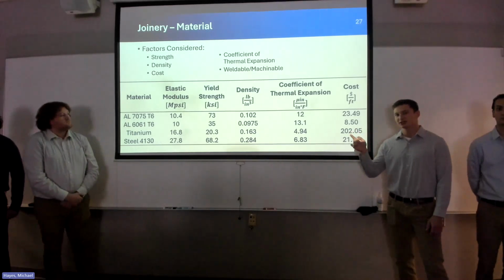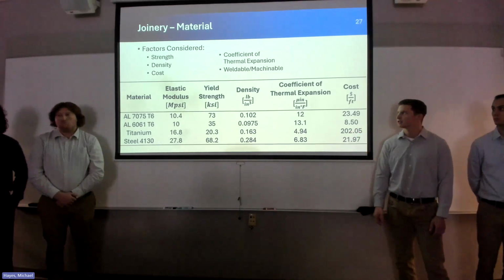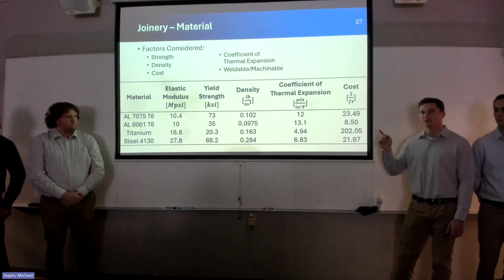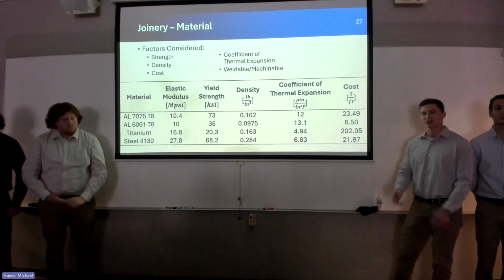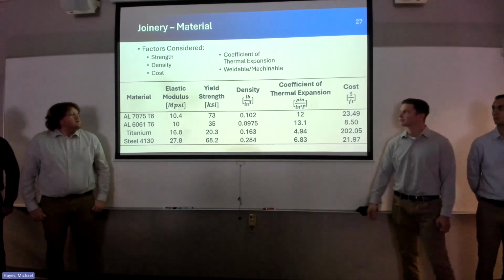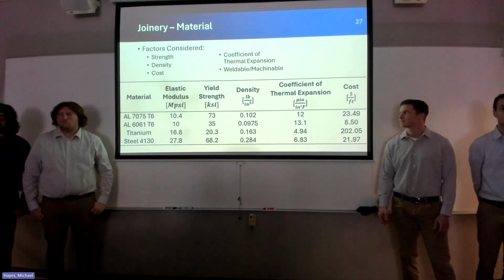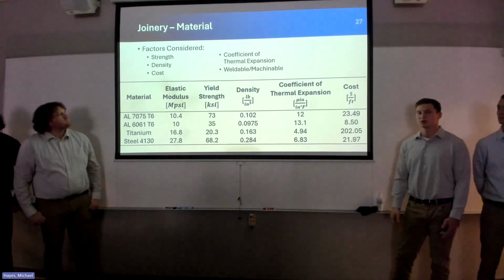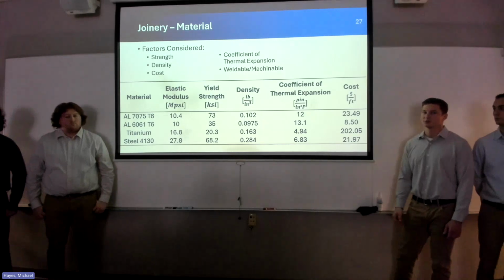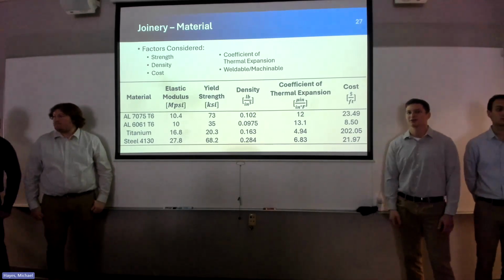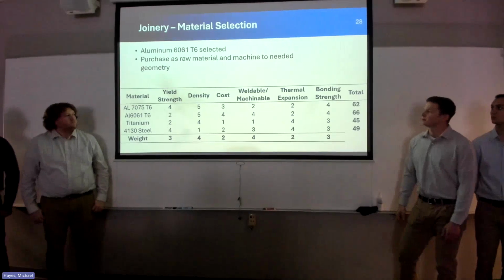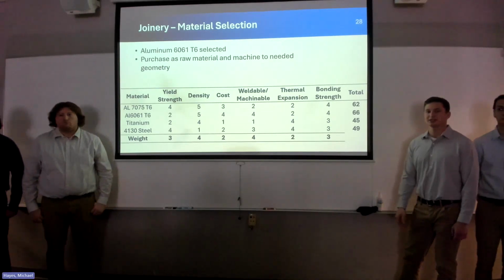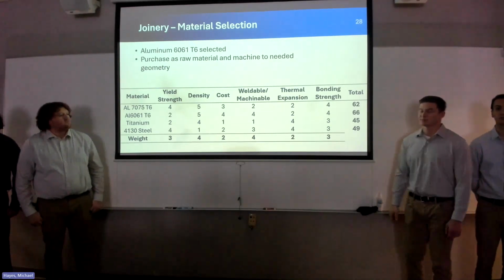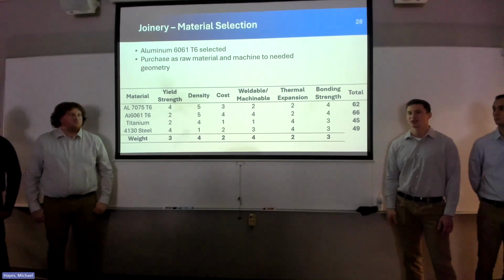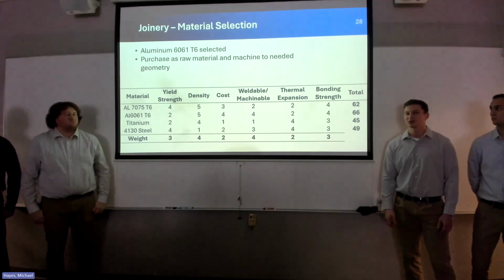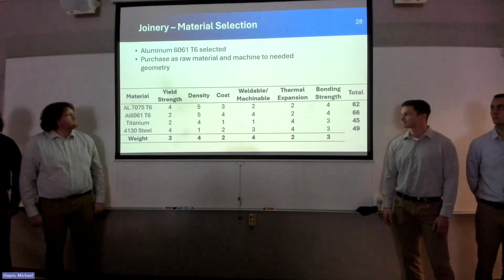Obviously, we wanted to consider the strength, density, and cost as these are main considerations. And again, that coefficient of thermal expansion, we want to make sure that it doesn't expand too much in comparison to the composite, just to make sure there are no residual stresses. Lastly, we want to make sure that it's actually weldable and machinable, as some of these geometries will be pretty complex. We don't want any work hardening limiting us in those factors. With our decision matrix, we ended up picking a 6061 T6 aluminum. This is purchased as a raw material, which we can get from pretty much any supplier, and then machine it down to whatever geometry we need for our later considerations.